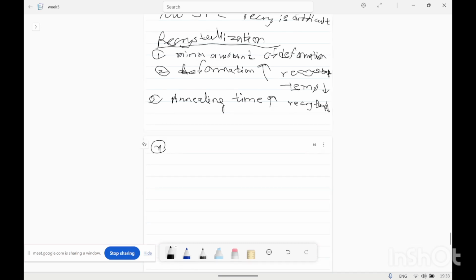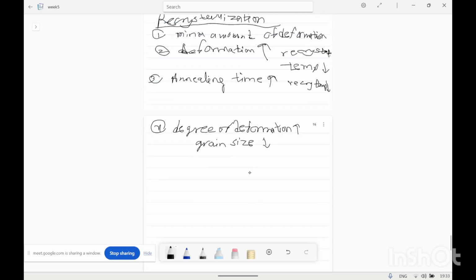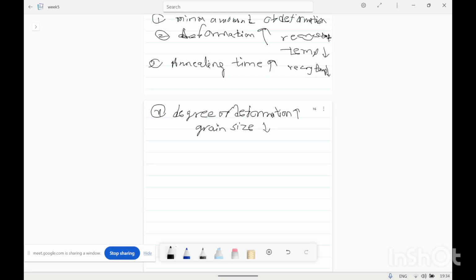Next is the grain size after recrystallization depends on the degree of deformation. Means as the degree of deformation is higher, grain size will be small, of the strain-free recrystallized microstructure. Also, the greater the degree of deformation and lower the temperature, the smaller the grain size, and low temperature will result in finer grain size. Finer grains after recrystallization.